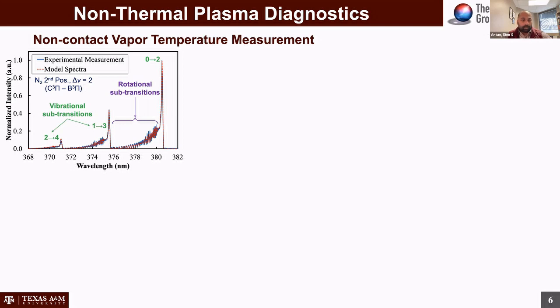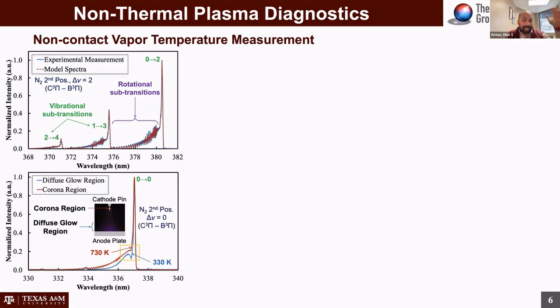And so using the spectra, and matching it to model spectra that was developed out of Stanford, we can do estimates of the plasma temperature. And as you can see, sometimes these plasmas are really high temperature. So at the main point in the plasma, the powered electrode in a sense, your temperatures approach 700 plus Kelvin. But what I observed way back when I did my master's was that if you take an unpowered